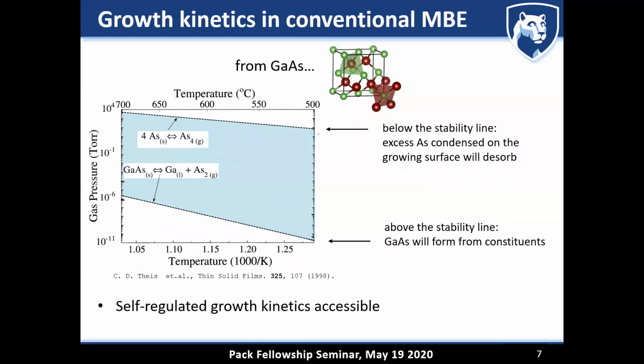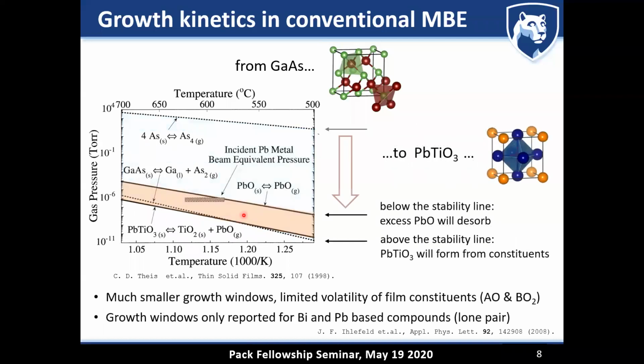And so if you use this idea of this growth kinetics that underpins all of the successful growth of molecular beam epitaxy, you can ask the question now, how's it going to look when you grow an oxide film? And really the take-home message, without talking about the details here, is that if you map the growth of lead titanate, which also is a perovskite structure, onto the same growth kinetics window, you're going to realize that now it's becoming much, much harder to actually hit your self-regulated growth window. You can see that now the difference in the stability line for the formation of lead titanate down here and making sure that excess lead oxide is going to evaporate, it's going to be much narrower.